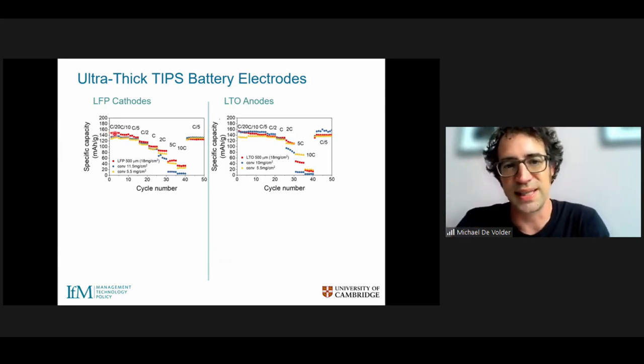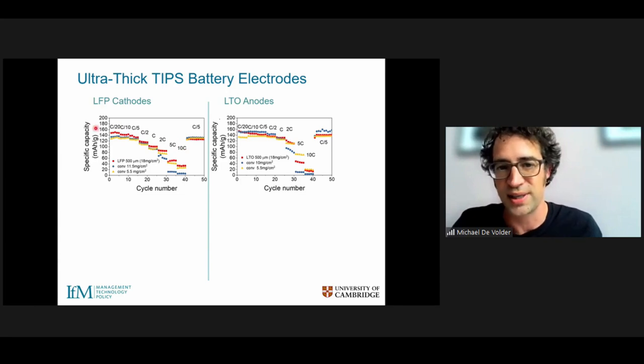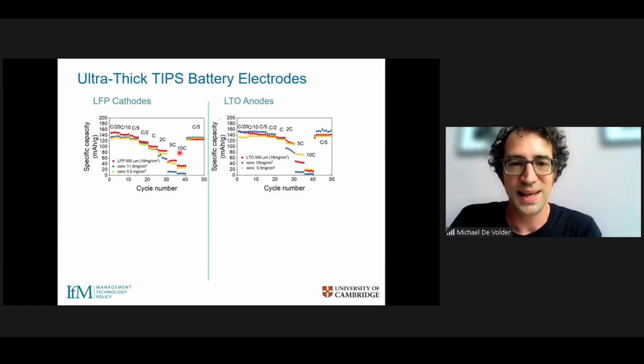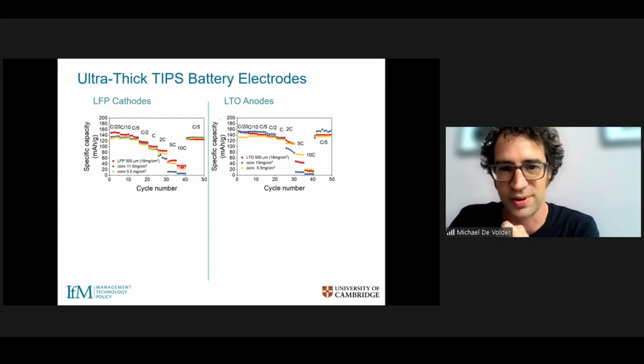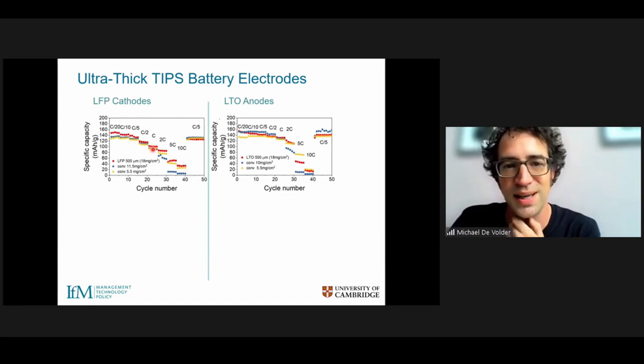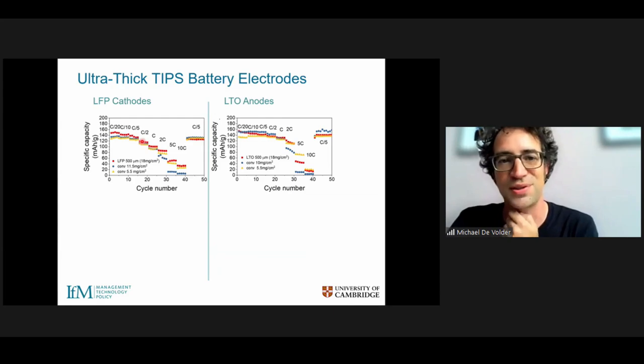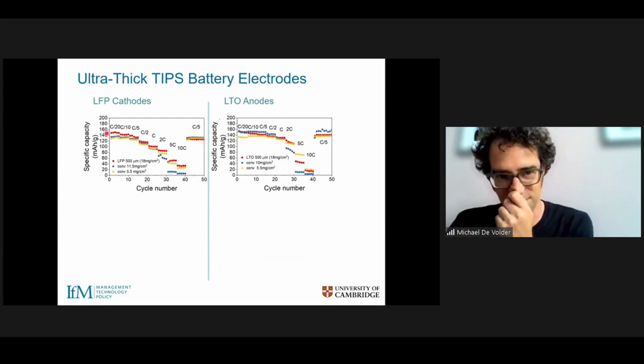The other thing I should show in this graph is that what you are seeing here with the C numbers is an indication of how fast we try to charge and discharge a battery. So 10C is short for battery researchers to say that you are charging your batteries in just 6 minutes. And so you can see that at 6 minutes, we can store a small amount of energy in our batteries, but if you do it much slower, so for instance, 1C stands for 1 hour charging, C/2 for 2 hours charging, and so on, we can store more energy in it.